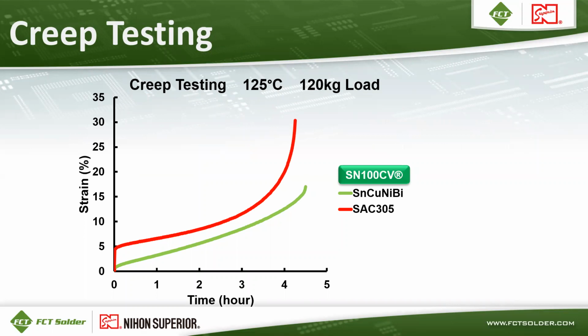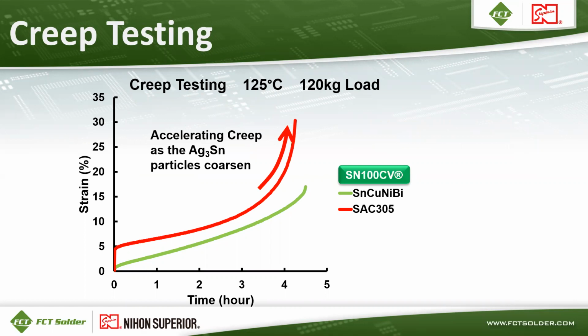Here's a chart of creep with SN100CV versus SAC305. SAC305 is the red bar and SN100CV is the green bar. This is strain on the y-axis versus time in hours on the x-axis. You can see creep accelerates, or the rate of the strain increases pretty dramatically over time for SAC305, because the Ag3Sn particles are coarsening during that, which accelerates the creep. Whereas SN100CV shows a fairly stable creep over the same duration of test.